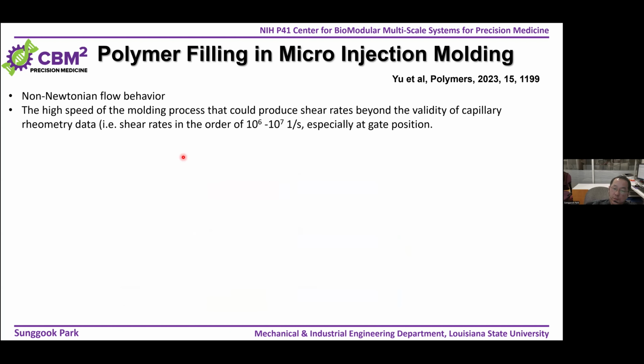But for injection molding, the filling behavior is slightly different, because we are not using the rubber state above Tg, but the viscous melt state above the melting temperature. There are two main differences from the flow behavior in nanoimprint lithography. First of all, the polymer behaves like a non-Newtonian fluid. Another thing is that in injection molding, you use a screw to inject the molten polymer into the mold cavities, so the filling rate or shear rate is very, very high. You have to consider these two effects when you analyze your data.